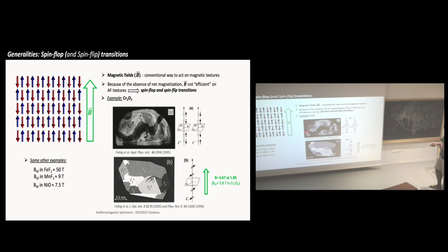Here I take one example. It's the very famous chromium oxide, Cr2O3, which is an antiferromagnet. In this picture, the contrast stands for 2 kinds of antiferromagnetic domains. This is what we call 180-degree antiferromagnetic domains. So either they are like this or they are like that. So you have white and black. And then if you apply a field large enough, here 6.6 Tesla in this study, you see that you change the contrast, and basically you go from this to this configuration, and this time they can lie in 3 possible directions. This is where you see the contrast. So this is an example of a spin flop transition.